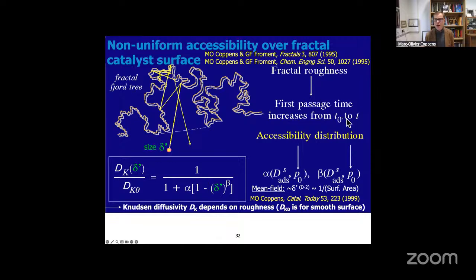And so how that first passage time changes depends on the accessibility distribution. You can derive an analytical model, which is what I did, and find a relationship between the Knudsen diffusivity as a function of the diameter of a molecule. The prime here is divided by the so-called outer cutoff of the fractal scaling regime, which for this alumina would have been 6 nanometers, in the example I showed. And this is divided by the one if the surface were smooth.